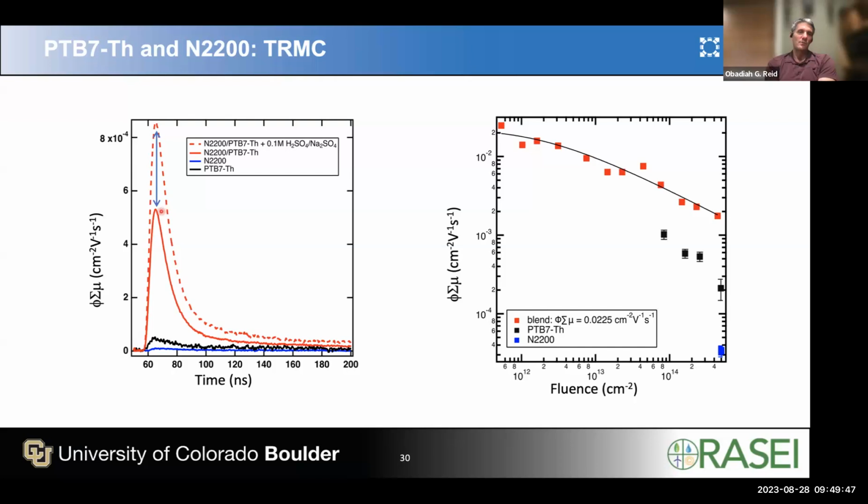And when we did that, we made this qualitative observation that, here's the neat acceptor, here's the neat donor, here's the blend. And then when we dipped it in the acid solution, we saw this significant increase in the photoconductivity.